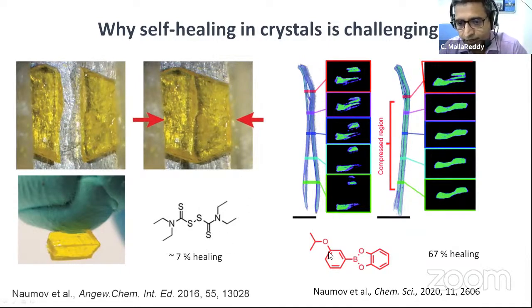And so here another molecule they have taken with these boron oxygen bonds, and again this is a very soft material. You again break it into two pieces by attaching two plates on either side, and then you pull it, you have a crack, and they separate. Then you push them together and keep it again for hours, and then you push them back. Then you see about 67% healing in this material. So these are only the two significant ones in the organic small molecule material.